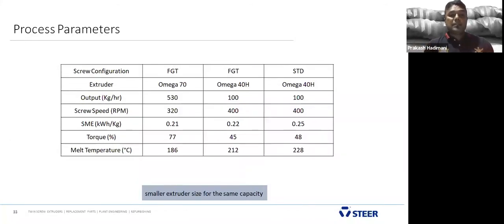This is a similar study we did in our lab, the comparison study I'm talking about. With FGT technology, we used a 70 millimeter Omega extruder, and FGT technology was also used on the 40 millimeter, so that we can compare the difference between the 70 millimeter and the 40. When going for a scale up, we didn't find much difference between the lab scale and the bigger scale. But we observed a difference with the standard technology.